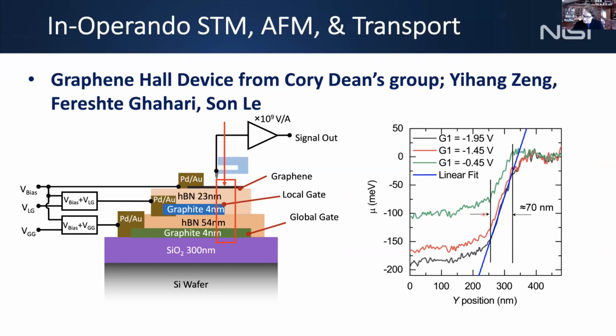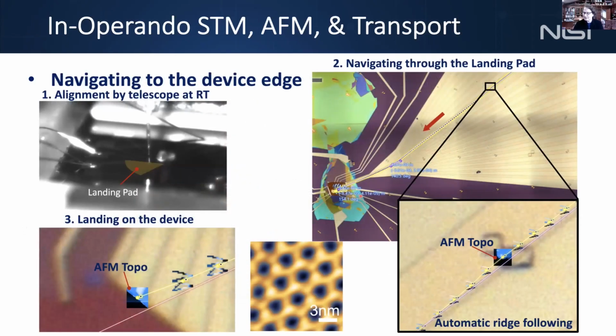So what I'll show you is that the same wedding cake profiles we saw in the PN junction rings, we'll see now in this potential profile. This potential profile will get reconstructed into a step-like pattern. And what's nice with the AFM is we can measure directly this chemical potential. So we're not measuring Landau levels, we're measuring directly the chemical potential. And we do the same navigation, we have the runways.